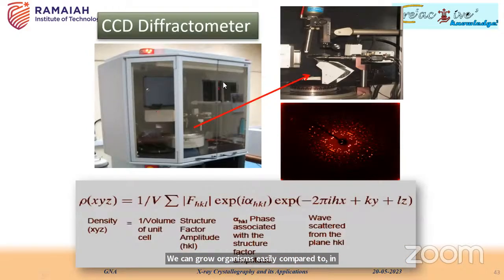And then a single crystal diffractometer is the instrument used. Here the tiny crystal is mounted somewhere here with the detector setup and the X-ray source. And this is the CCD plate, image plate, where we observe the diffraction spots, which are collected on a CCD plate as an image. We collect hundreds of such images by rotating, oscillating the crystal in all possible orientations, so that we collect lots of data. And finally, it is processed.